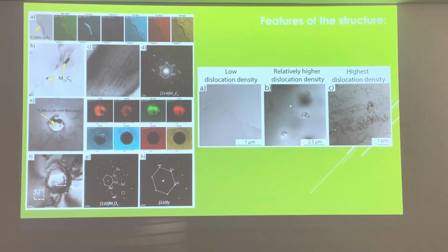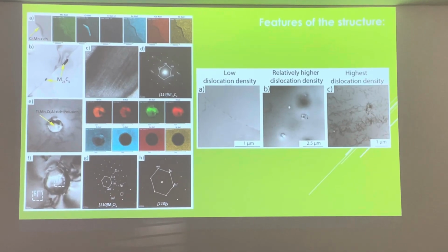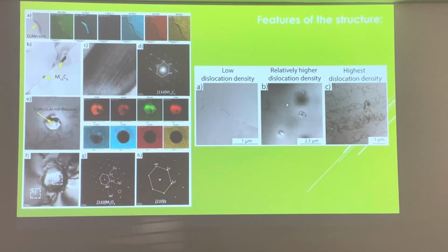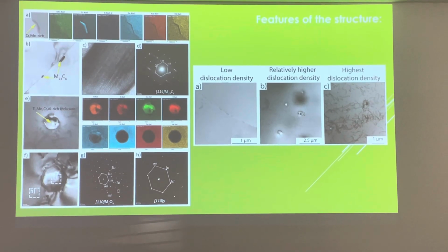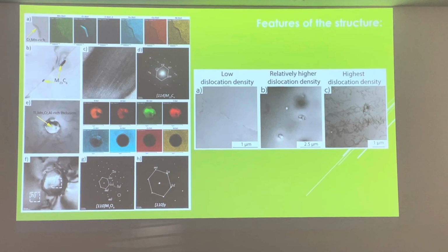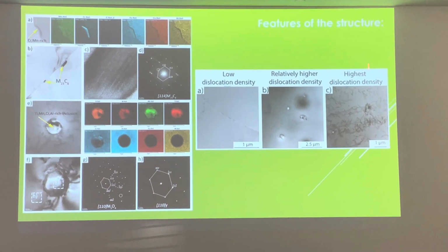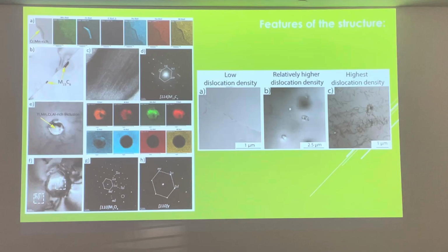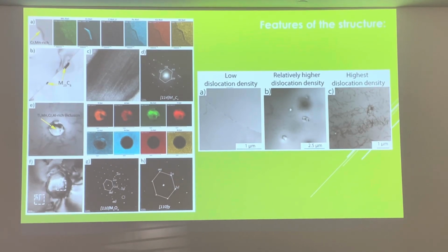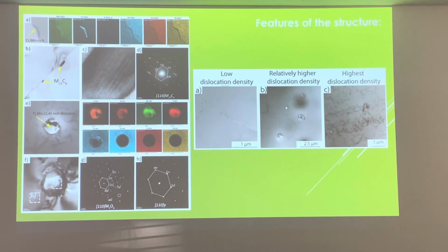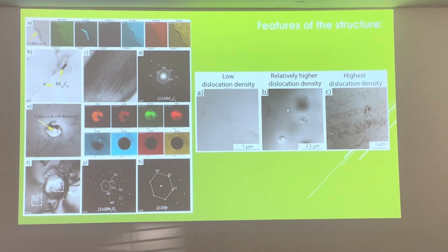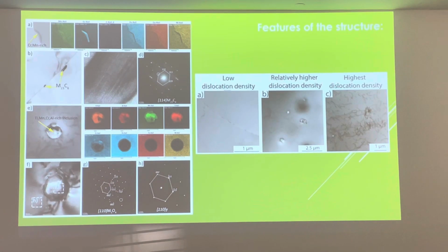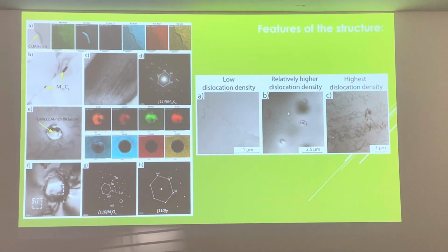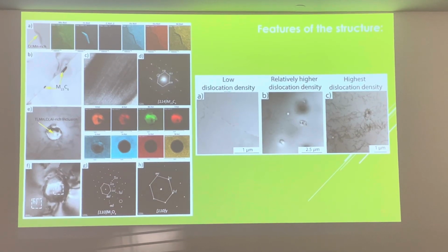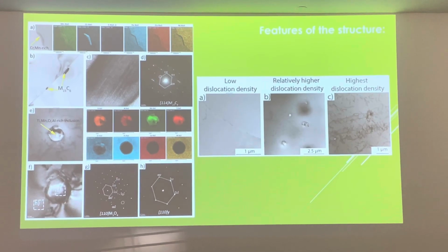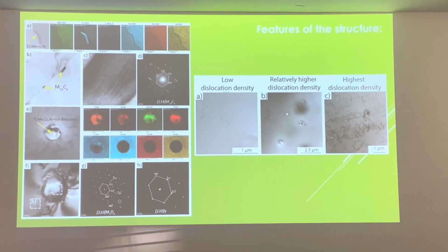Next, the next level of microscopy is transmission electron microscopy, where we also saw the distribution of dislocations in the bottom, middle, and top part, and the same dependency. At the bottom part, there are almost no dislocations, low dislocation density, and moving toward the top, we have observed an increase of dislocation density. It is also connected with the solidification process.